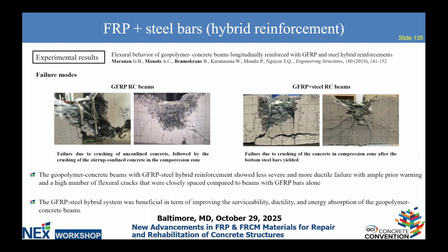in a way, if you look at the single stress-strain curve, you have a very good post-peak softening. When they did the test, they could see that you have an overall more ductile failure because the governing material crushing was of the concrete, and because of the better post-peak, you have overall a better performance.